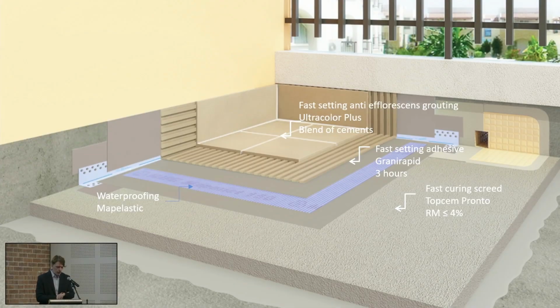Okay, so this is a possible stratigraphy we can have. We have the waterproofing system, we have the screed. Of course, we can also adopt other types of material than the classical one to fix the tiles or prepare the substrate. So the waterproofing system is blocking the water, okay? But maybe you can also change the system adopting a different binder for the substrate which has a residual moisture lower than 4% after 3 days.